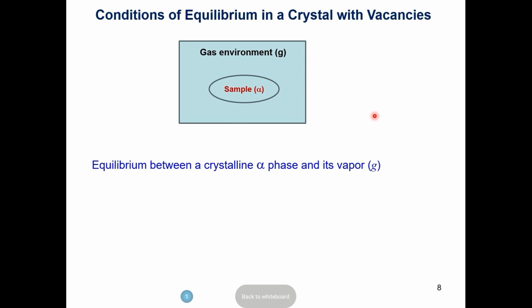And I'm going to talk about the equilibrium level, the amount of point defects you create that is in equilibrium with the environment. You will see that one of the conclusions will be that if you take your sample to high enough temperature, where you create a certain amount of vacancies that are equilibrated with the environment—meaning the oxygen partial pressure, the gas environment, and the temperature—the equilibrium amount of vacancies gives you the chemical potential of the vacancy.